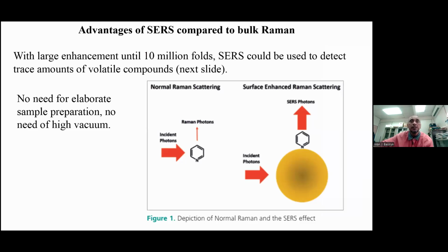For example, in this case, you have the Raman photon. When this molecule is adsorbed onto the gold structure, then you measure the scattered radiation. That scattered radiation is measured not in the same direction as the incident photon. The incident laser passes the molecule in one direction, and the detection is in the opposite direction, I mean, not on the same plane as the incident photon. So that is the detection strategy.